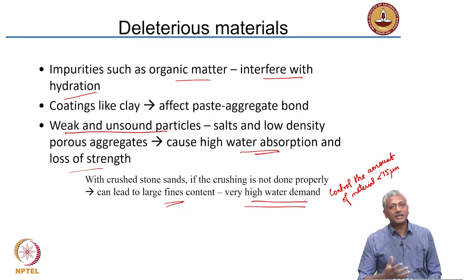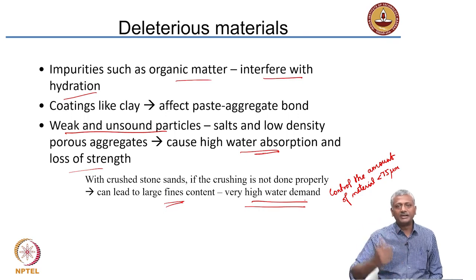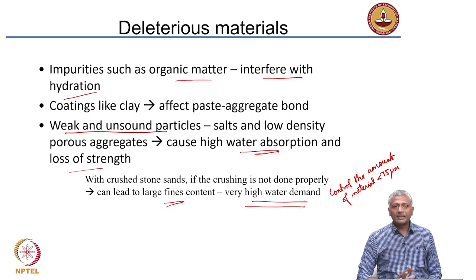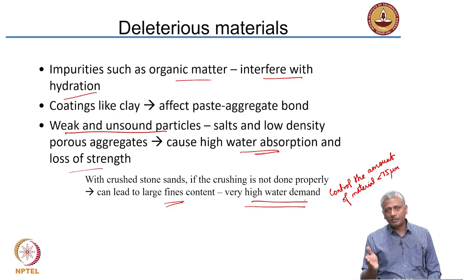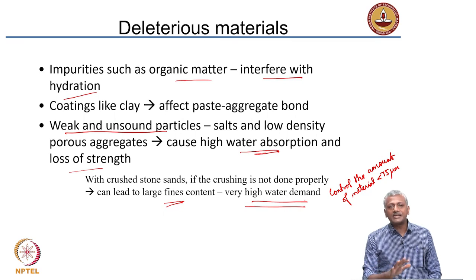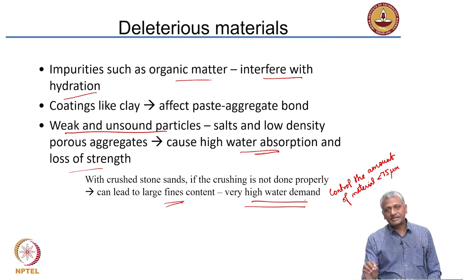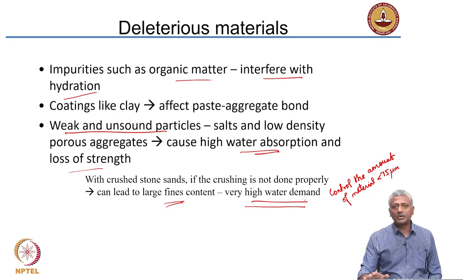In river sand, you typically do not get this problem because the action of the river nicely washes off the very fine particles. However, apart from that one problem, in most cases crushed stone sands can produce concrete of as good quality as river sand. Crushed stone sand and river sand produce nearly similar concrete quality, except that you may get more fines with crushed stone sources.